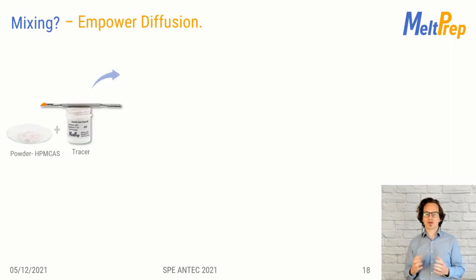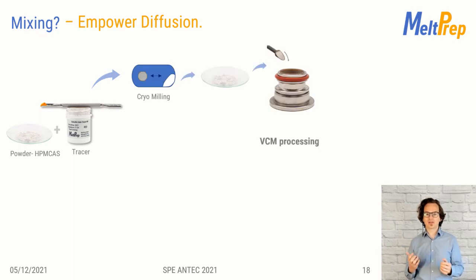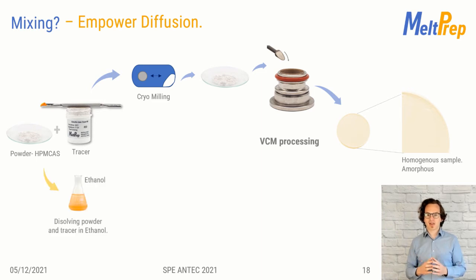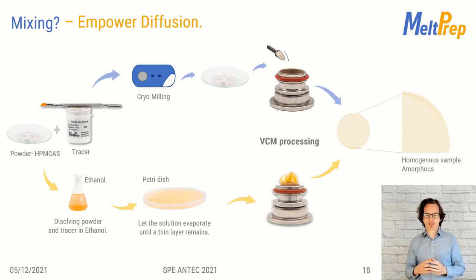The way how we usually recommend doing so is milling, preferably cryomilling. Reducing the particle size before processing via VCM will let you obtain an extrusion-like result. In the pharmaceutical world, often an amorphous transparent disc. Another option is solvent casting. We dissolve the mixture in a suitable solvent and let the solution evaporate. Take the remaining film off from the petri dish and put it into the VCM tool. It will also shape it in a completely homogeneous disc that is extrusion-like and suitable for further investigations.